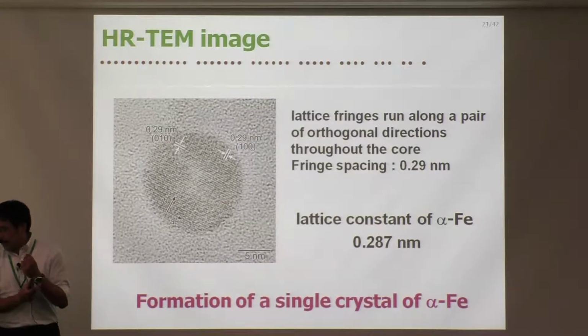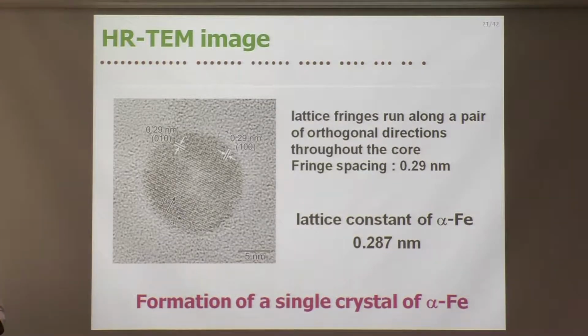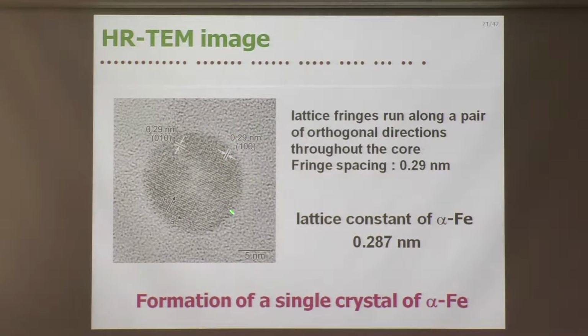Here shows a high resolution TEM image of the alpha-iron nanoparticles. As you can see, nice atomic images can be observed throughout the nanoparticle, and no grain boundaries are there. So from this result, the alpha-iron nanoparticle formed is a single crystal of alpha-iron.